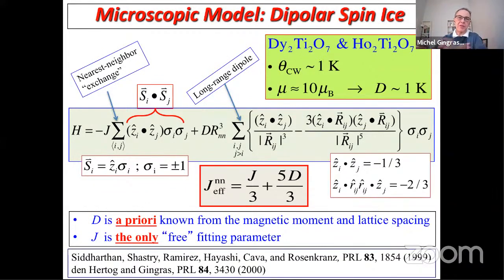And so the first model that was put forward to try to explain what's going on in these materials is the one that's written in this green box here. It's called the dipolar spin ice model. It really has two terms. It's quite simple to explain. The last term, apart from the mathematical details here, really just describes the physics of the long range classical interaction between Ising dipole moments that point in and out of a tetrahedron. And so the sigma i here are Ising variables. They simply identify whether or not the spins are pointing in or out on site i.